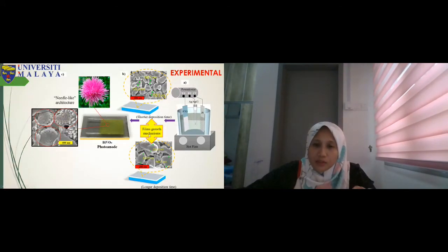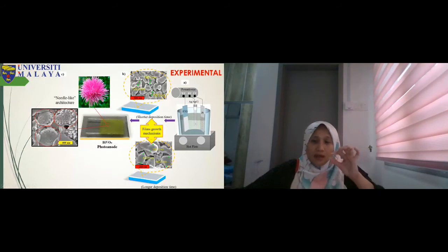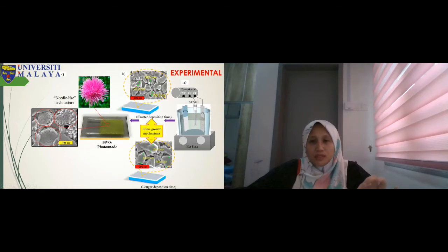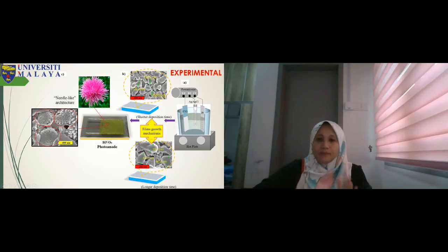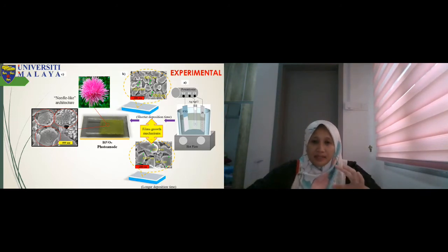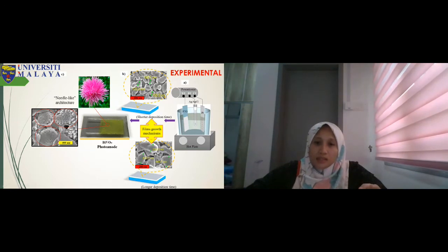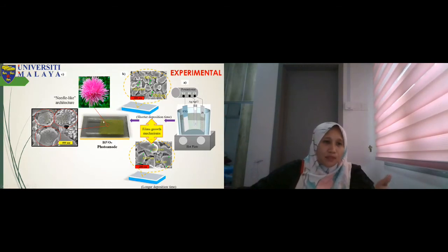This is for the shorter deposition time. This shows the film growth mechanism. For the shorter time, using the FESEM we can calculate the diameter of our nano flower, and it is about 148 to 175.2 nanometers. After we prolong the deposition time, we can observe that the diameter is getting bigger and bigger, around 333 to 449.7 nanometers. This is our bismuth vanadate photoanode. It looks yellowish, a beautiful color. After we send it to FESEM analysis, we can observe a needle-like architecture.